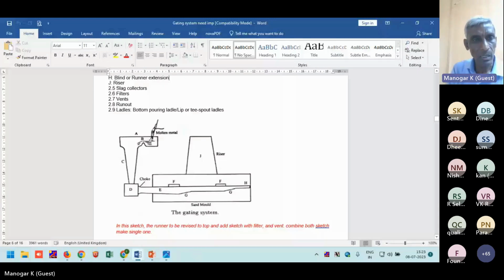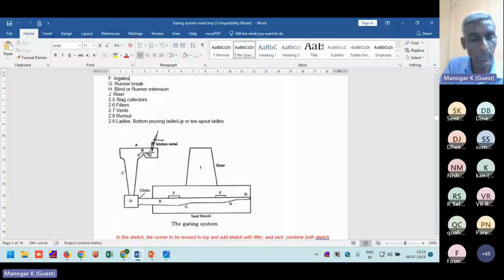the sprue extension, sprue base, pouring basin is required for all the bigger castings, and vents for all bigger castings and core prints where there is no open riser. And for heavier castings, you have to go for a bottom pouring ladle.